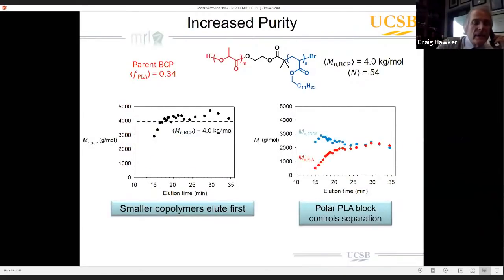And if we look at each one of these samples individually, you can get a sense for what is happening. The length of the dodecyl acrylate for all of the samples stays about the same. Maybe it decreases just minimally. But if we look at the relationship between the amount of lactide and the elution volume, you can see that it increases fairly consistently. So in essence, it's the polar polylactide block that controls separation. We also see that the smaller copolymers elute first.